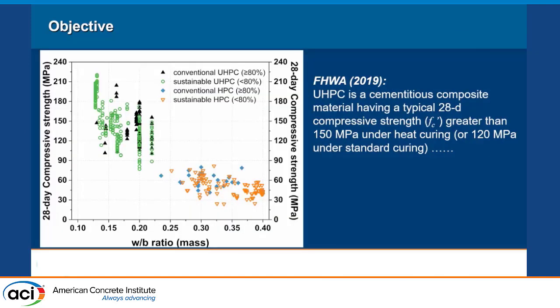According to FHWA, UHPC is a cementitious composite material having a typical 28-day compressive strength greater than 150 megapascals after heat curing, or 120 megapascals under standard curing. As we can see here, I plotted the compressive strength of UHPC and high-performance concrete with respect to water-to-binder ratio. There's an obvious gap between these two categories. And if we regard UHPC with a cement content less than 80% by weight of total binder, we may find that people prefer to decrease the water-to-binder ratio to achieve even higher compressive strength.